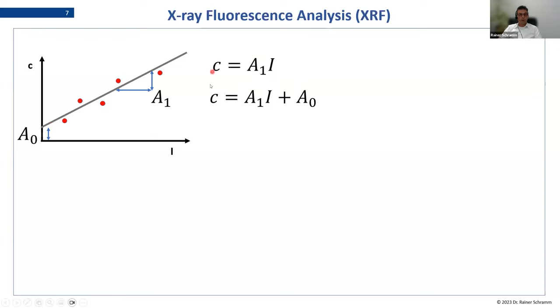And so then the formula becomes like this, that we have our measured intensity, we have our slope, the sensitivity, and then we add our offset, which has the unit concentration, and this is why it is representing also like a blank value. So easily in a calibration, you could change the blank value just to shift around your calibration.